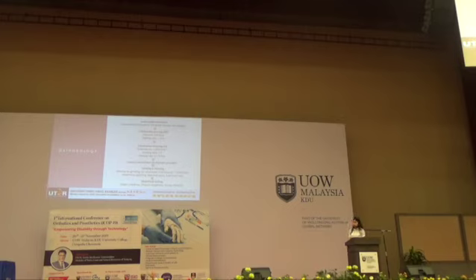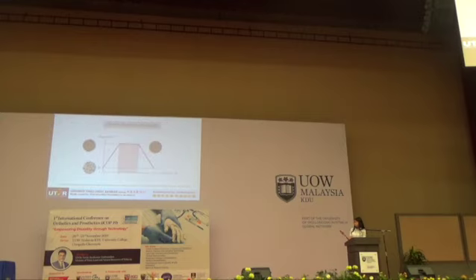This is the sintering profile. The green bodies, you can see the green particles. There are a lot of pores, and when the temperature is slowly increased, reaching the sintering temperature and held for a period of time and cooled to room temperature, the pores are eliminated and clear grain boundaries are formed, which means high density.